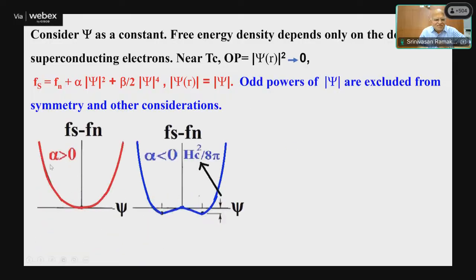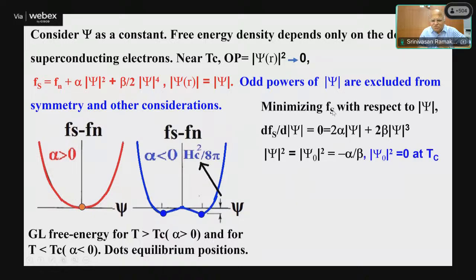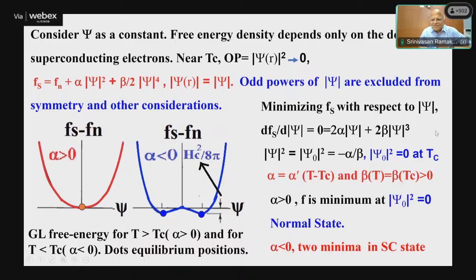So the free energy, where alpha is greater than zero, will look like this in the normal state. When alpha becomes less than zero, you will see that the minimum splits into two minima. Minimizing the free energy with respect to psi, you will see that psi naught squared is equal to minus alpha by beta. Alpha is negative because it goes as T minus Tc, and we are looking at temperatures less than Tc, so alpha will be negative. These are the expressions which they could find for alpha and beta. You see that when alpha is less than zero, there are two minima in the free energy.